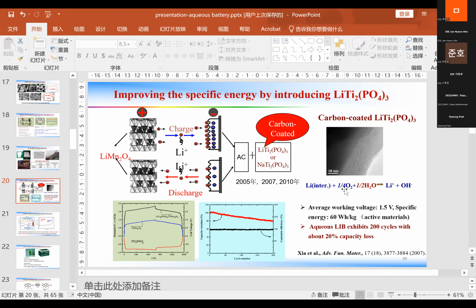So we must remove the oxygen. Like mine, we use sealed systems. Another way is to remove the water, but removing the water is impossible because we are in a water electrolyte. So there must be water, but we use a carbon-coated layer. This is not a porous carbon layer. This carbon layer allows lithium ion intercalation, but it can prevent water transport because there are no pores, only crystal defects. So it only allows lithium intercalation. But if we use low heat temperatures, the electrical conductivity is low. If high temperatures, it becomes graphite, which is a layer structure.